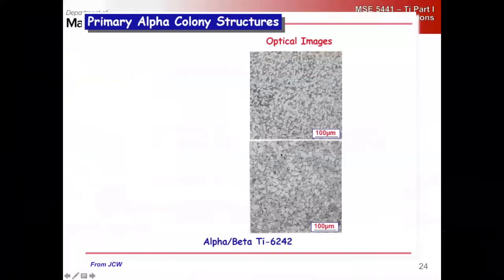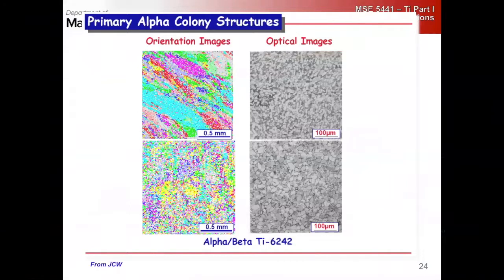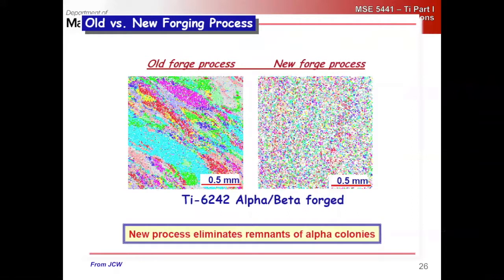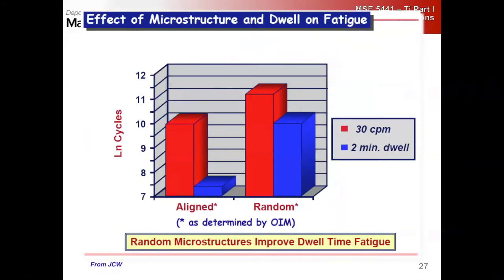Last Wednesday we left off talking about this macrozone formation in forged titanium, right, where you had large groups of alpha grains that had similar C-axis orientation, right? So you had these large regions that essentially acted like a single grain, and how new forging processes were developed that put a lot more strain into the material, right? And that really affected the dwell fatigue life quite significantly in these parts.